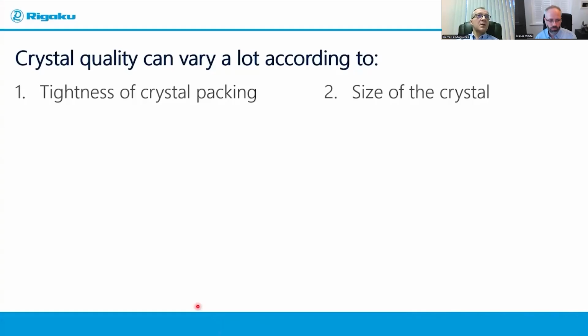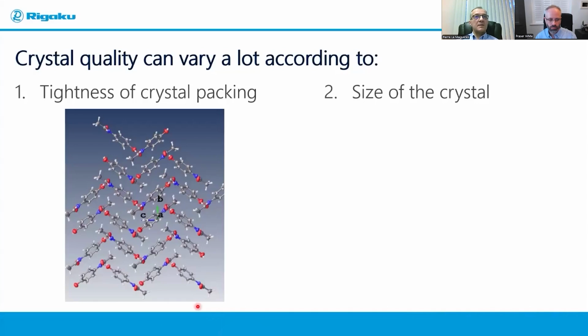However, of course, nature being nature, not all crystals behave that well, and then the crystal quality will sometimes be much poorer and even too poor to get good data. So crystal quality, really how well a crystal diffracts, is mostly influenced by two criteria: the tightness of the crystal packing, or the packing of molecules in the crystal, and also the size of the crystal. Okay? So here is, again, the picture of the crystal structure for that specific polymorph of acetaminophen. And you see how tightly the molecules are arranged with each other in the crystal form. And really, it's not hard to understand how such a small and flat molecule can get a tight packing in the crystal form.